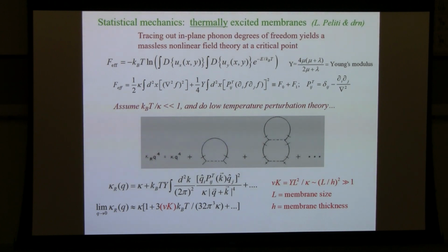What you can do is to sum up the most diverging diagrams at every order in this perturbation theory. Here's the most diverging at second order, at third order, and so forth. If you sum that up, you get a self-consistent theory for an elastic, so-called elastic constant. This renormalized bending rigidity would then appear on the right-hand side, down here in the denominator. And if you just solve that self-consistent problem as a function of wave vector, so you look at the response to things as a function of wave vector, you'll find that the bending rigidity diverges.